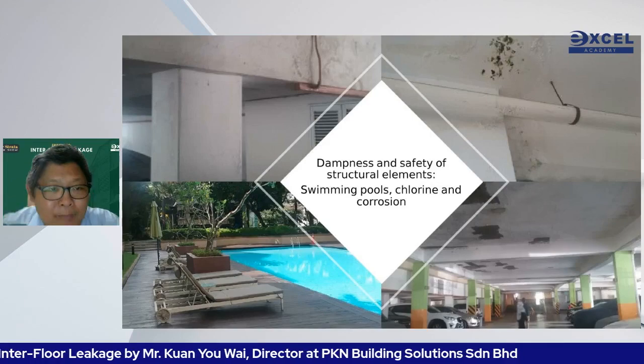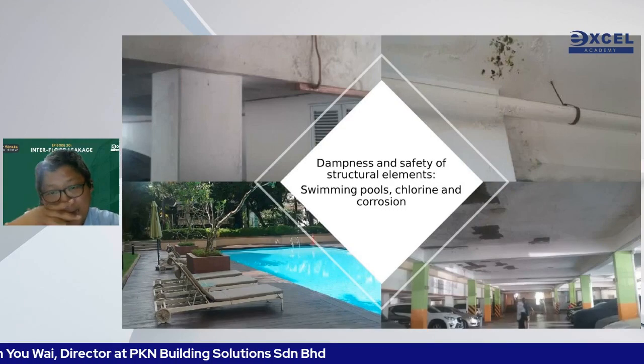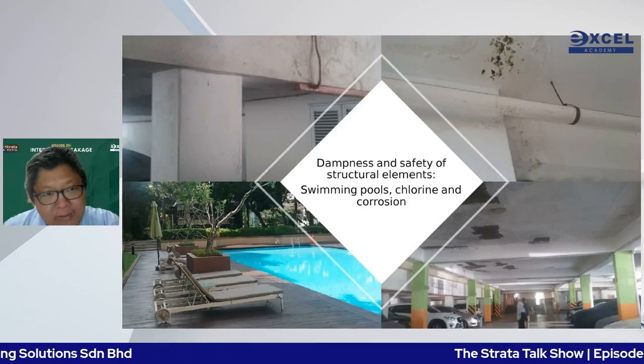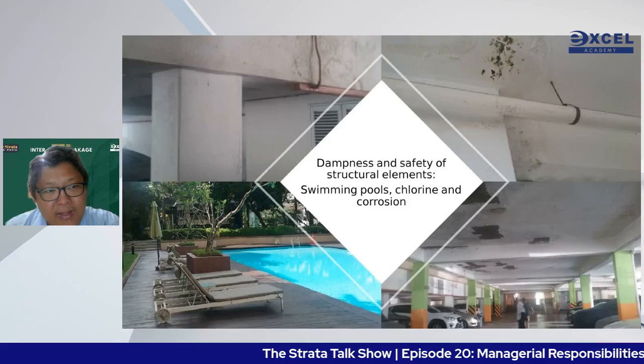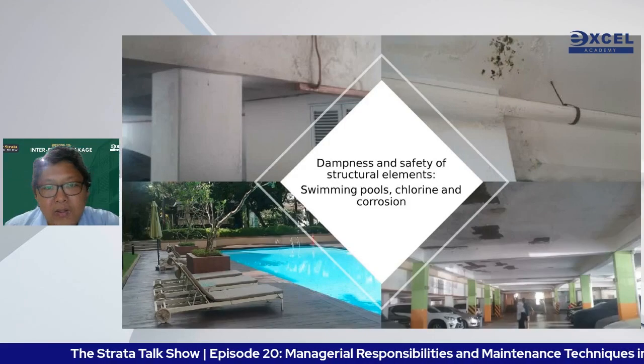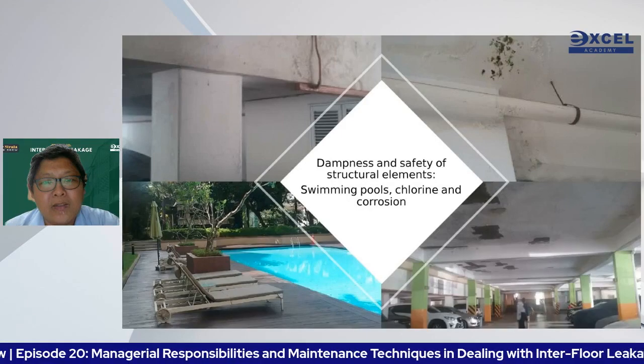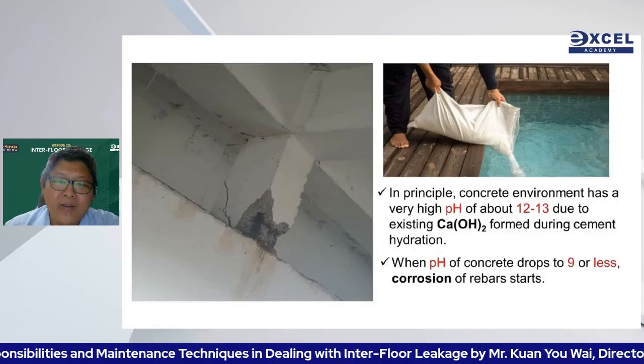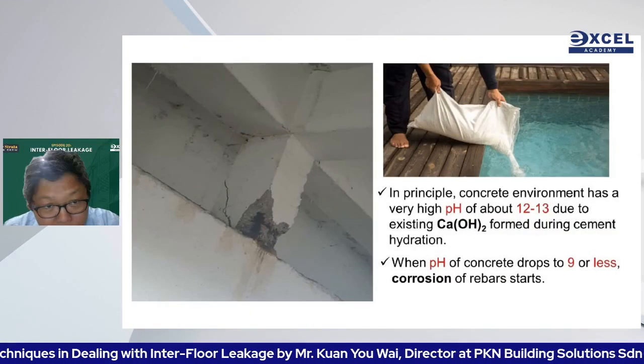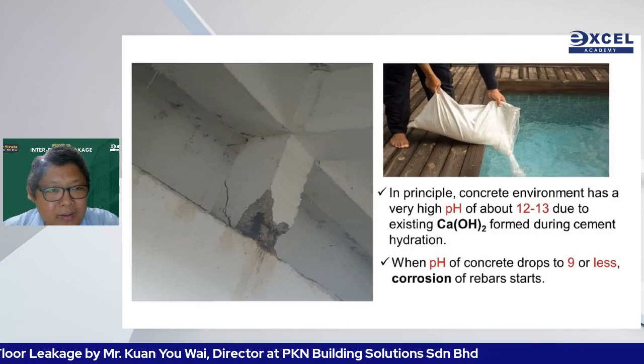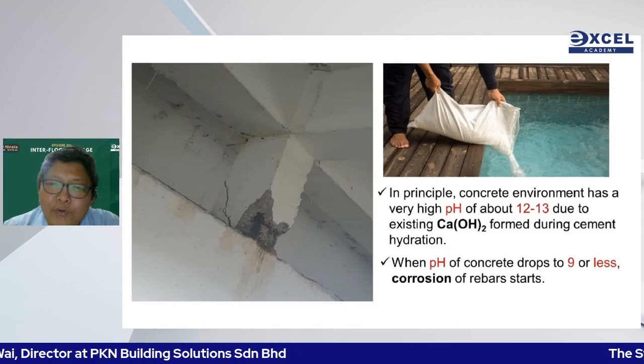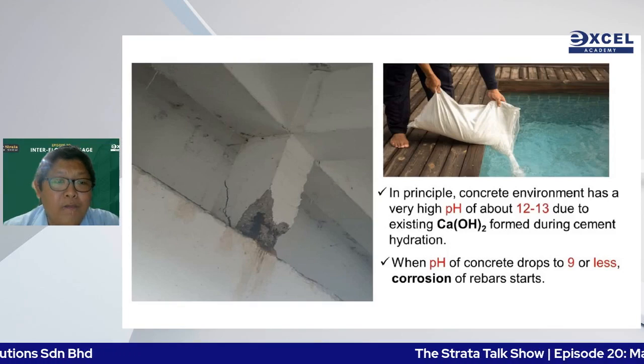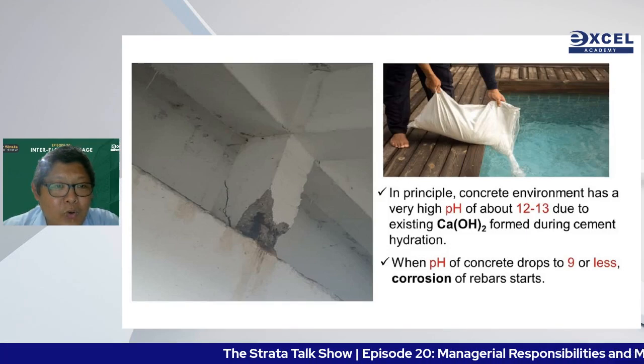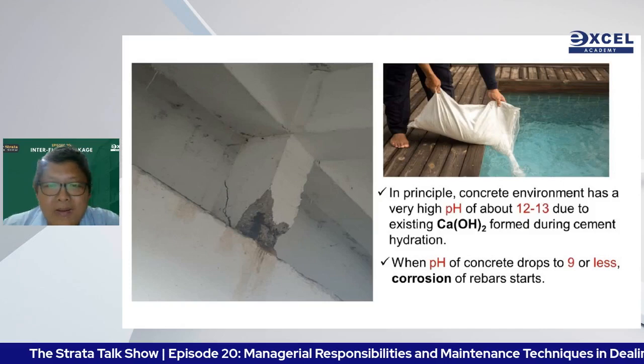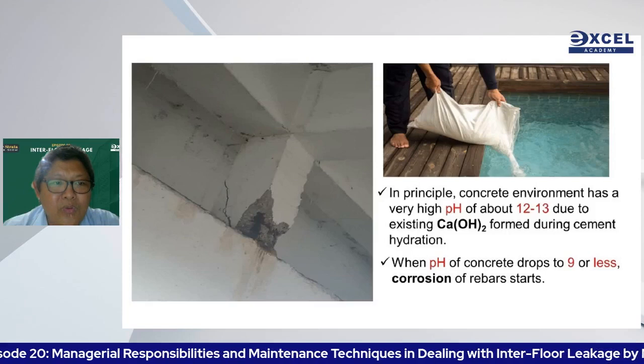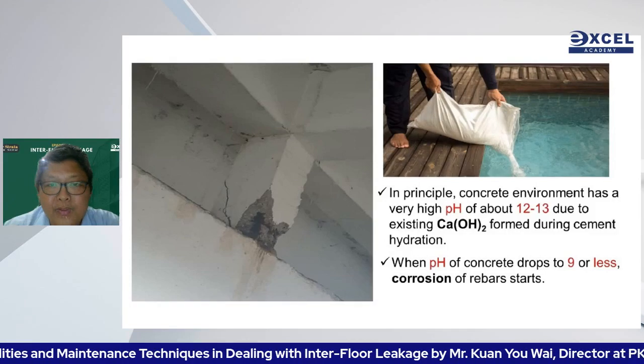And it is 2.5 times heavier than air, so it always floats on the concrete deck. So when it encounters water, it becomes hydrochloric acid, attacking the reinforcement steel bar, your waterproofing and your concrete. So that's why for waterproofing in a swimming pool, if it's not chemical resistant, it's disastrous. Okay, next slide. And it can cause damage to concrete, so badly like this. And this could be a structural issue, okay? But unfortunately, most of our structural engineers are not aware of corrosion engineering. Some of them don't even see corrosion as a risk, you see. Very sad to say, but this is covered under EN 1504, which I will explain to you in the next slide. Next slide, please.